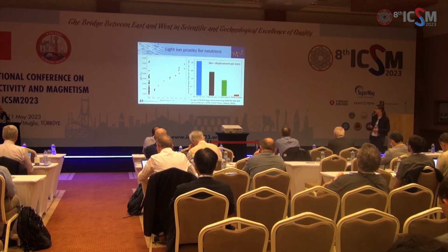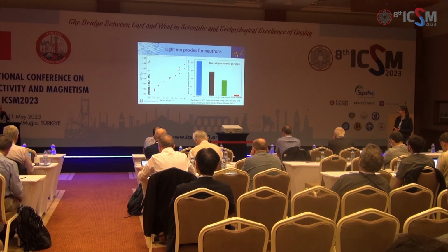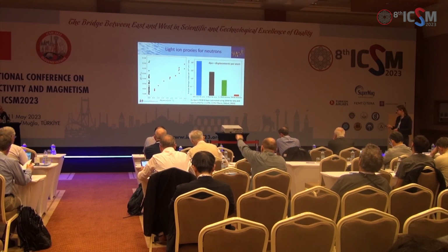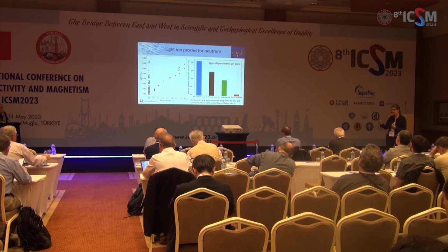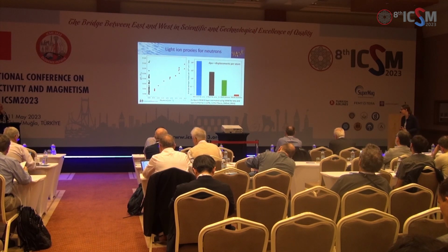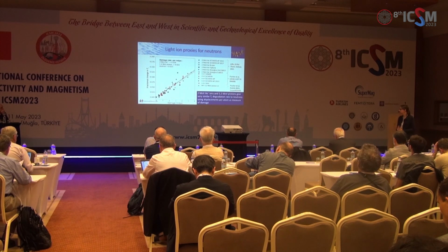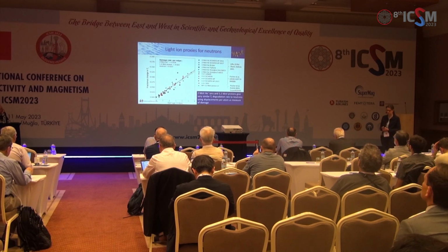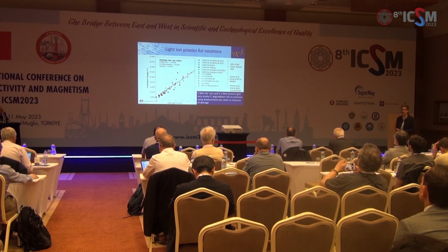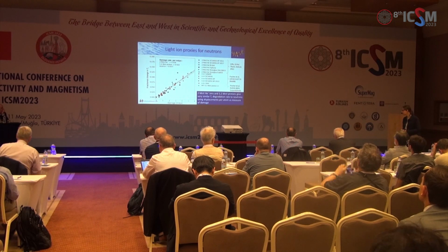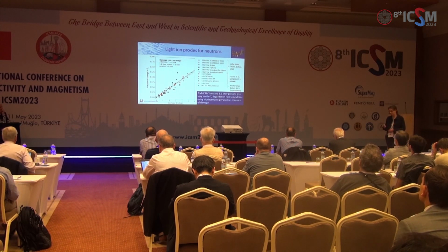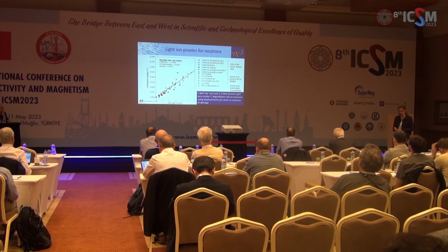Well, because these different projectiles interact differently with our material, they produce damage at different rates, and we can use simulations, Monte Carlo simulations, for example, to work out how much damage we would expect from different ions of different energies. And when we do that calculation, we can convert our graph on the left here to something in terms of average damage, which we measure in something called displacements per atom, or DPA, which is how many, on average, displacements of atoms within your material you have as a result of that irradiation. So if we do that scaling to a DPA scale now on the x-axis, now our ions look to be having much more similar effect to the neutrons in terms of the change in TC. So that's encouraging in terms of using ions as a proxy for neutrons, that at least we've got some scale that we can compare the damage on.